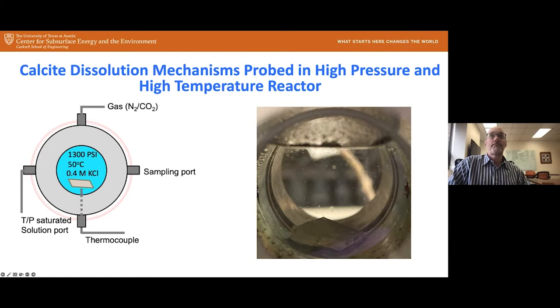So for this, we had a high pressure and temperature reactor. It's a little different conditions. It was at 1300 PSI, 50 degrees C, so it's supercritical conditions. We have a 0.4 molar potassium chloride brine. In this case, we're looking at dissolution of a calcite slab on the right. We're interested in the etch pits that are forming on the surface.